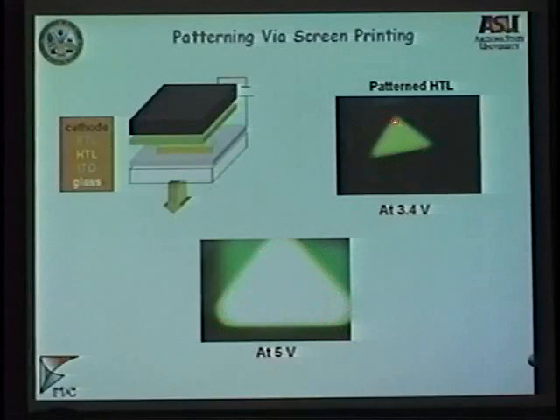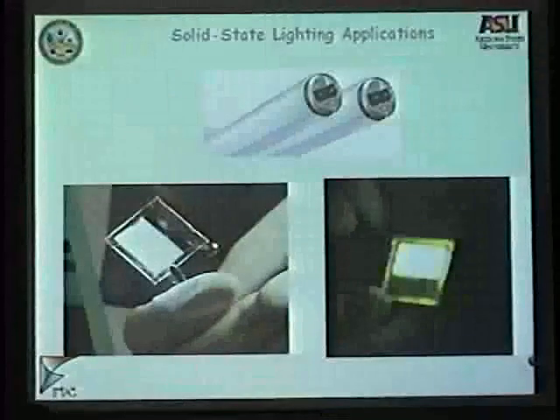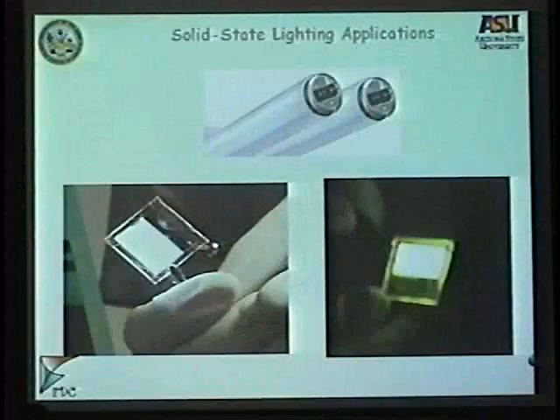At low voltage it looks much better. At high voltage the light starts guiding inside the device, and that's why you see this diffusivity here. This is not necessarily from ALQ, and our camera doesn't do fair justice to this because it filters out the yellow a lot, but you could see it here at low brightness, 3.4 volts only, and this is screen printing, right? This is the traditional printing technique for soccer jerseys and for many other applications.